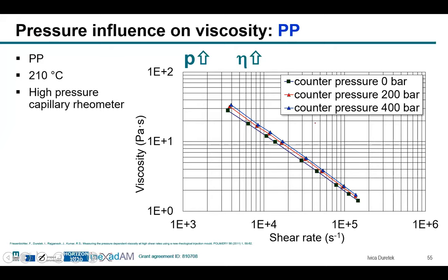The pressure influence on viscosity, again on polypropylene, for example at 210 degrees. These measurements were done at the high pressure capillary rheometer. Using the counter pressure device, we have realized counter pressures up to 400 bars. And you can see that if you increase the pressure, for example to 400 bars, the viscosity increases approximately 25% in this case of the polypropylene.